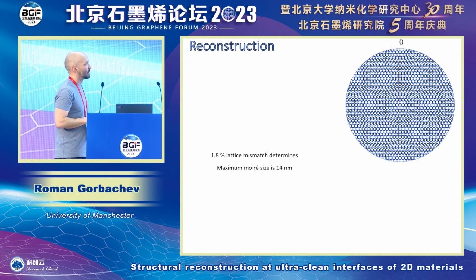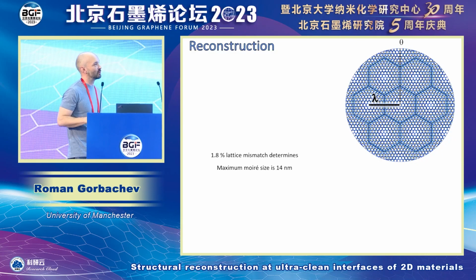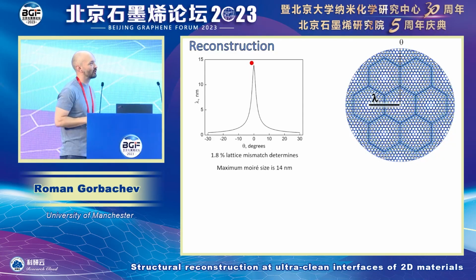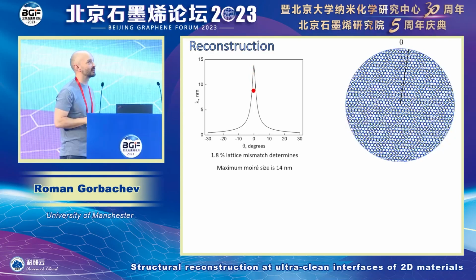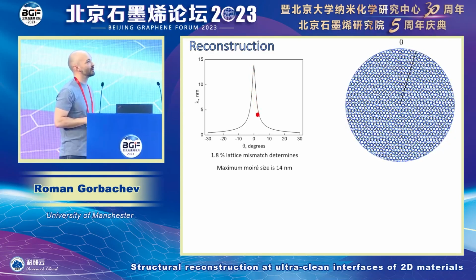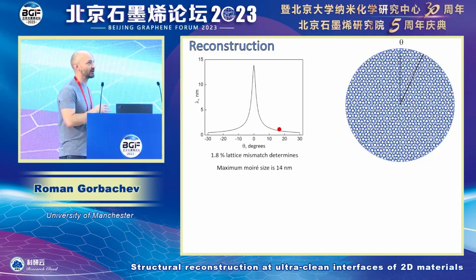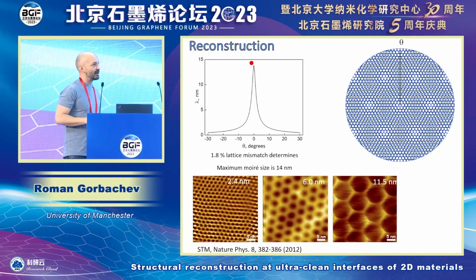Now, just to say a few words about the superlattices. Here's the basic superlattice with graphene and boron nitride. I'm sure you're familiar with this, but in very short summary, when you put materials with similar lattice constants on top of each other and you rotate them, you can see this superlattice appearing, a super period. However, it's not that simple, because when the lattices are very closely matched, there are more favorable regions in terms of energy and less favorable regions. And what happens is that they sort of click into perfect alignment